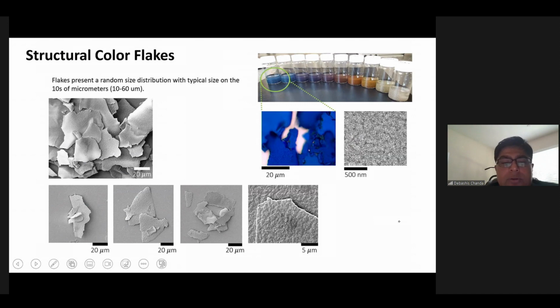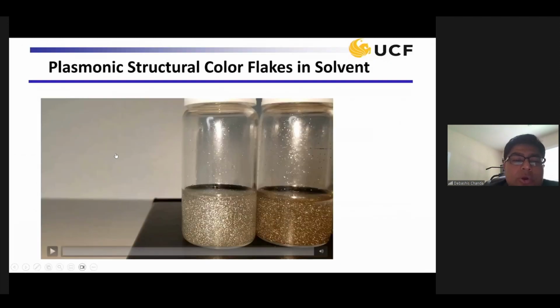Now, when you make this pattern, we need to mix them with resin to make it a paint. So what we do is flake them up. These are the kind of flakes we are looking at, which are replacing the conventional pigments. These are the colors from blue to, say, white or silver, with other colors in between. If you take a closer look, they simply are these flakes. You can control the size. We make those flakes out of these self-assembled sheets of 5-layer stack, so they all have this 5-layer structure built in, and they're about 10 to 40 micron flake size, which you can control based on the application. But the whole point is that just by changing the nanoparticle size, the aluminum size, you can produce these colors. So this is a video just to show.